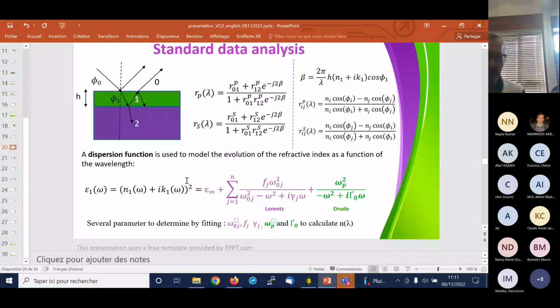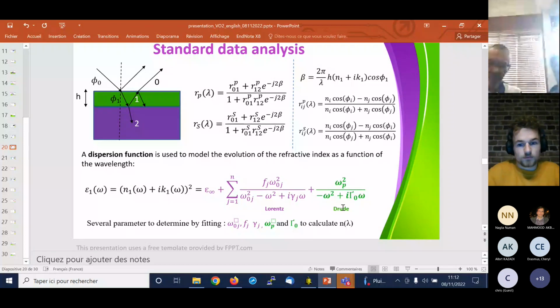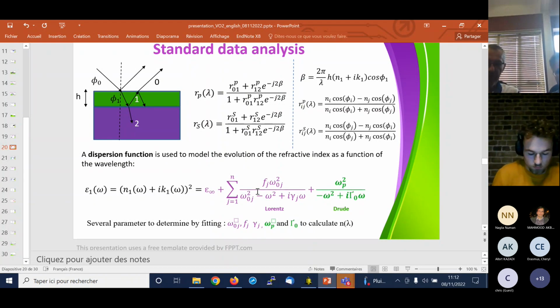Yeah, so you see here in this case, one way of describing the index of refraction would be to use this type of model in which you consider that you have, for the Drude component, free electrons. And here, this is typically what you can get for oscillators with energies in the infrared range. So this is what people usually take. But as Guillaume was mentioning, the main problem with this is that if you don't really know the good way of describing the index of refraction, then this Drude-Lorentz model is not very adequate.